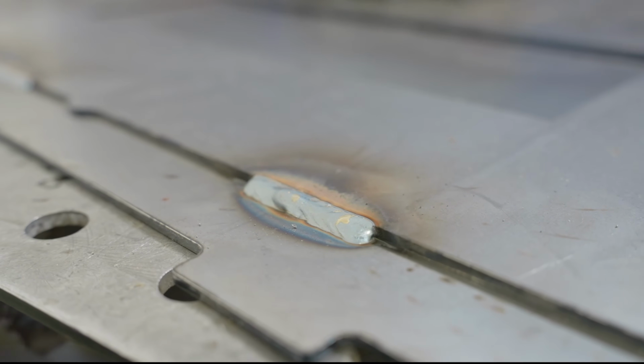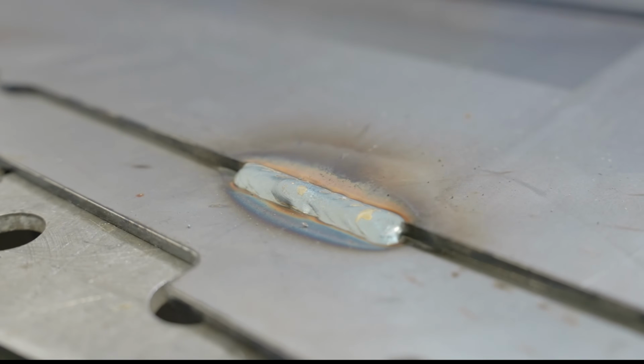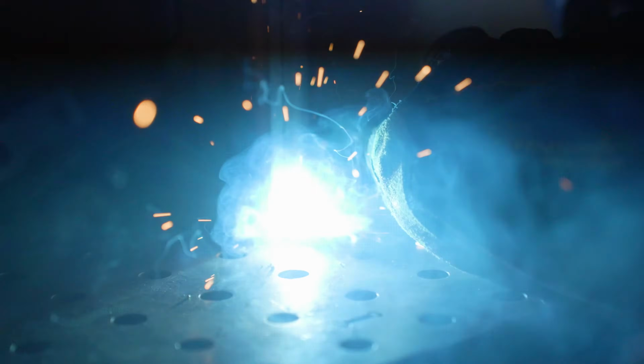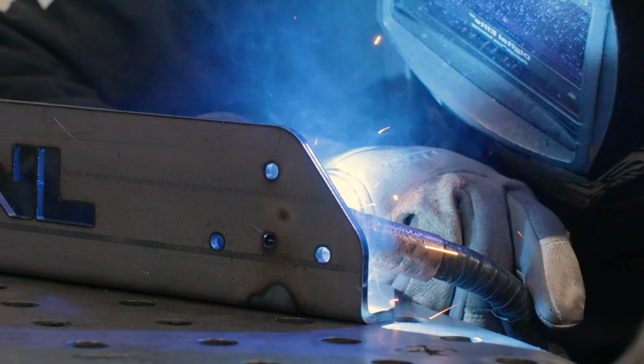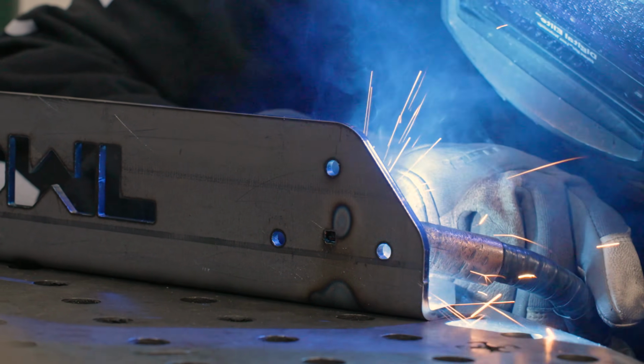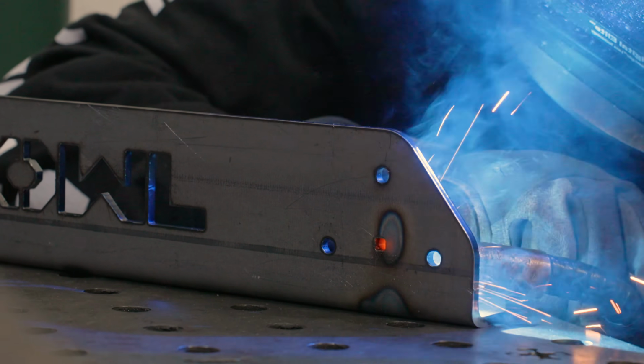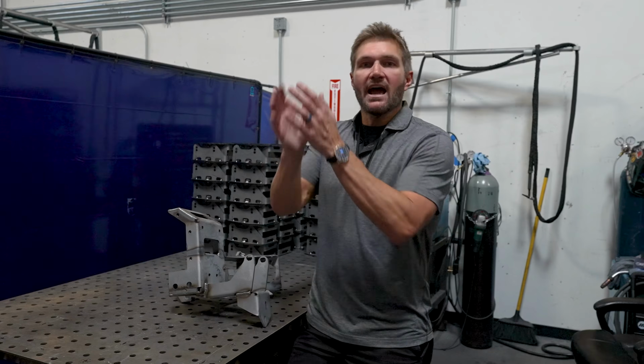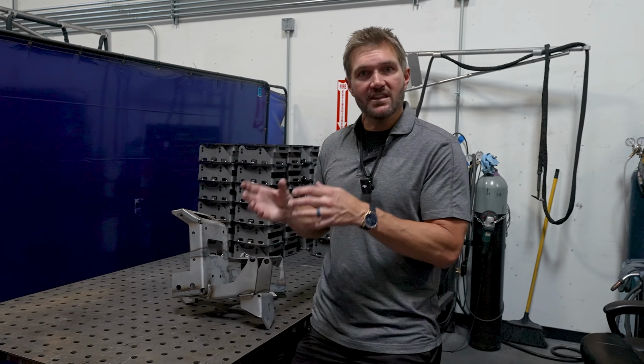That's because the metal wasn't hot enough. When you start a weld, it's going to be a little bit proud of the surface, and that's because the material is not hot enough to let the molten metal really soak in, let the weld soak in. And so whenever you start a weld, you're always going to have a cold part of metal. And then as you travel, the metal heats up and the weld really gets in there, and that's what makes it strong. You want the weld to mix with the steel.